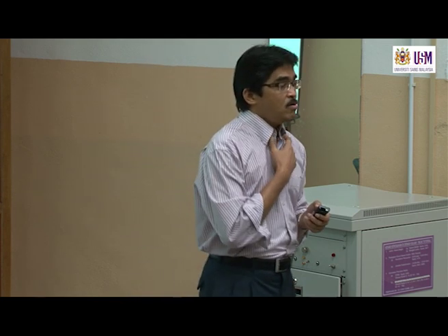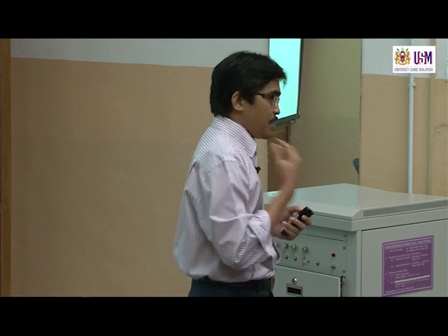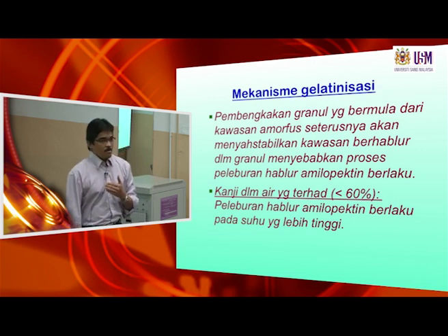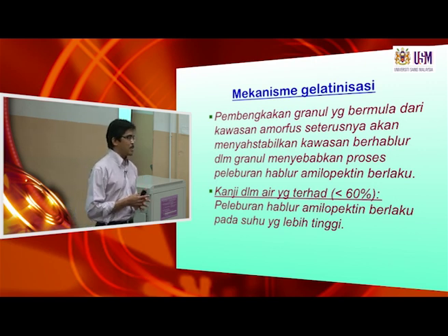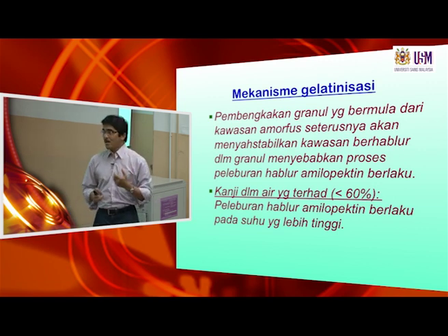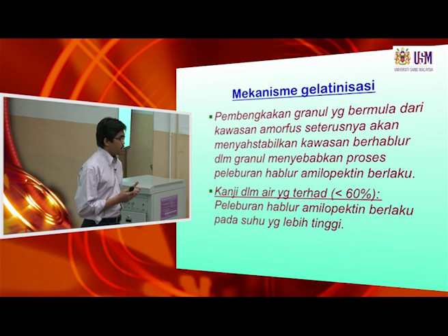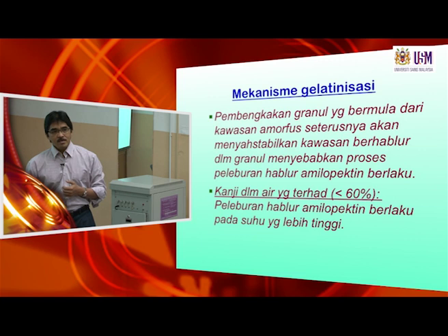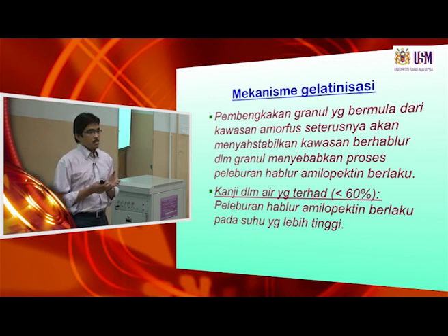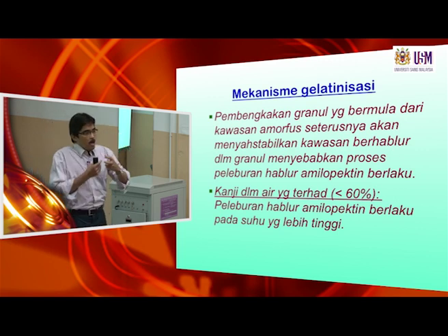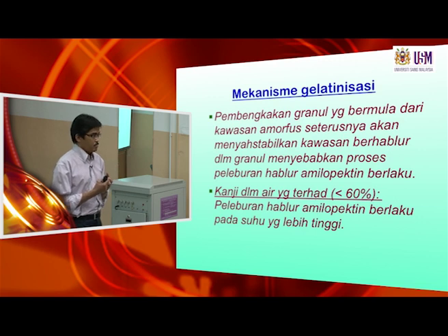So this is in excess water. What will happen now, or how would the mechanism differ in limited water content, less than 60%? This part explains the limited moisture or limited water content. Now, if we have less water or very low water content, maybe just about 30% or 20%, this small, lower amount of water would not be enough to destabilize the amorphous phase. So what would happen? At low moisture content, we need a higher temperature and longer heating time so that we supply enough energy, because the crystalline phase now requires a higher amount of energy to melt the crystal.